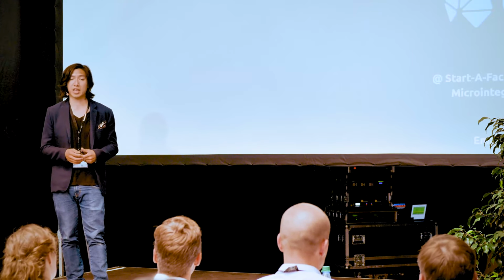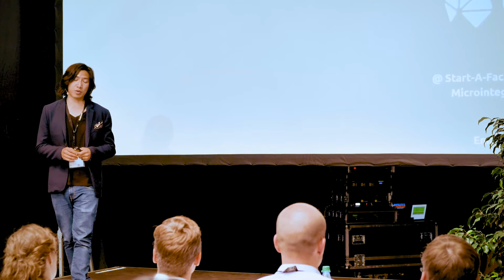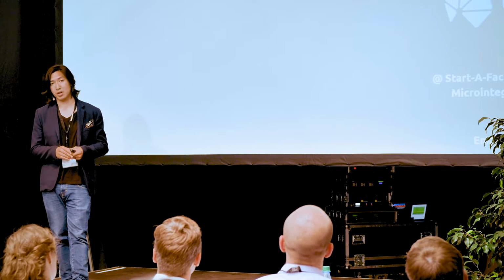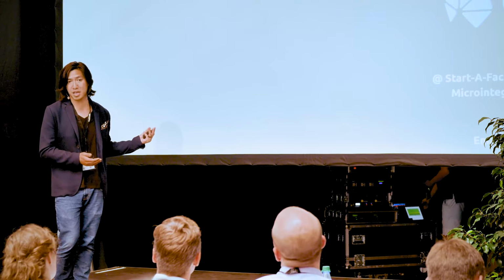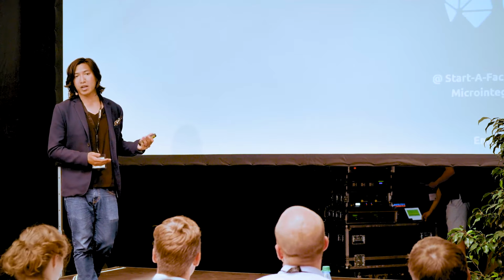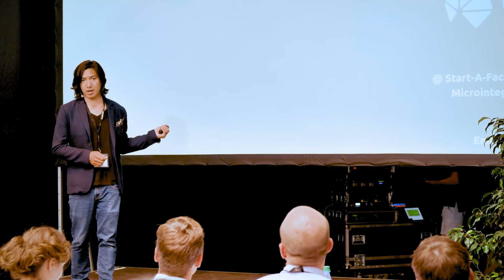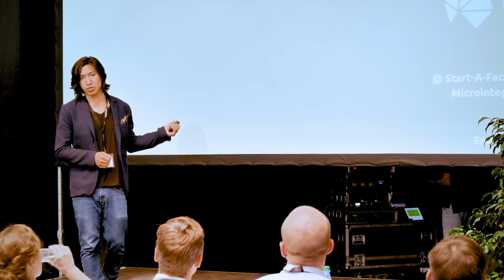This really helps with increasing interlayer bonding and minimizing delamination. If you look at our prints, they don't delaminate, so we're looking at near isotropic strength. This is the key difference, because we've already spoken to a couple of Cubesat companies based out of Berlin, and they have been working with our competitors, and they're not that satisfied with the results. They also usually have to do a post-process, because PEEK is a semi-crystalline material. In order to achieve a crystalline structure, you have to elevate the temperature for an extended period of time. Otherwise, it just comes out brown and amorphous. You don't have to do that with our machine. We get fully crystalline parts that don't need to be annealed.